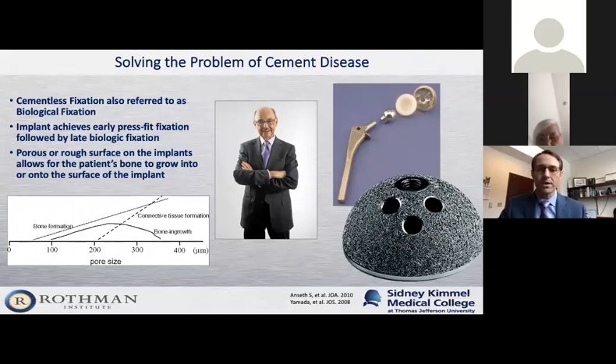implants. The premise behind today's cementless hip replacement is that you get immediate stability by press fitting the implant into the bone, which means that we essentially make a space that is slightly smaller than the actual implant so that it gets press fit in there and your bone kind of gives it a big bear hug, holding it in place while your bone then grows into the implant over the subsequent 6 to 12 weeks.